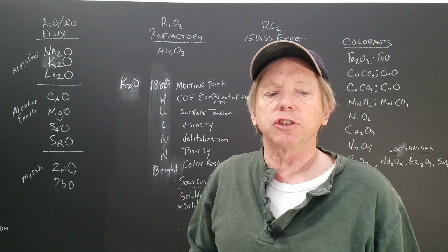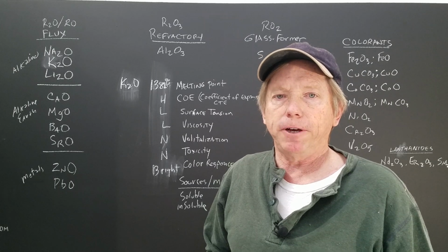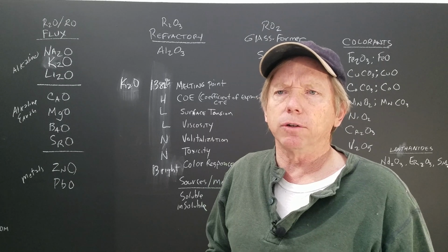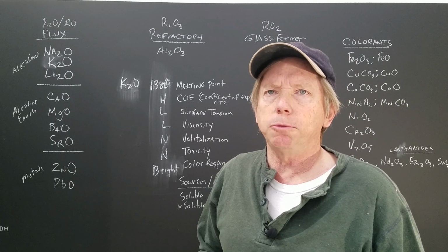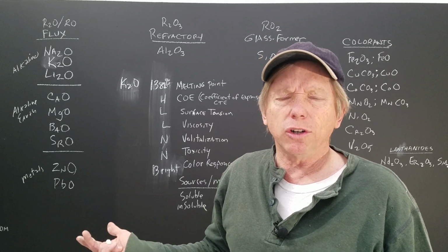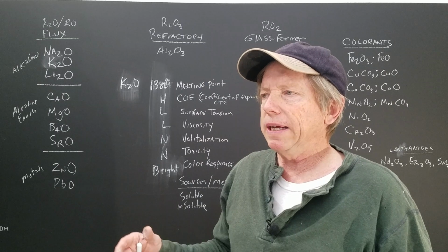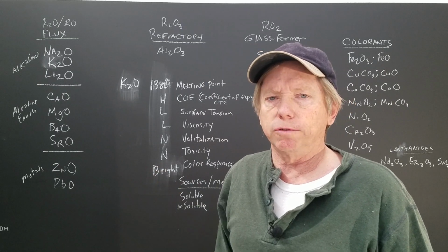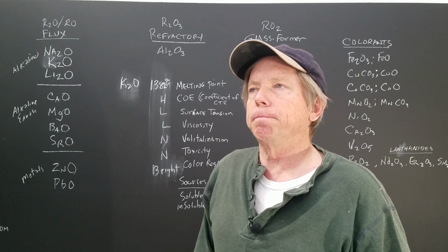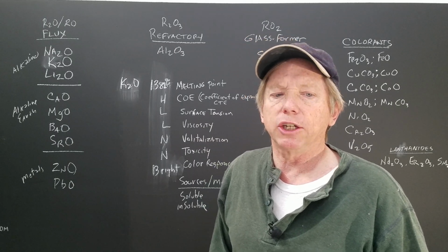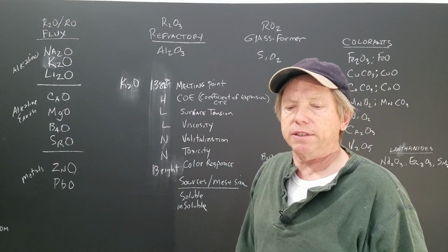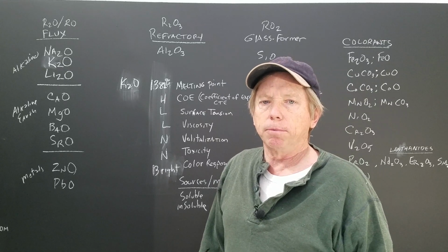Okay, and then the source of that would be potassium feldspar. Custer spar is the main potassium feldspar. Other ones might be Mahavir feldspar, G200HP, G200EU. Well, you can also get it in like Cornwall, plastic Vitrox. These are other sources of potassium. And the soluble source is potassium carbonate, pearl ash. Okay, one of the main nice things about potassium, it makes nice copper blue reduction, copper blue glazes.